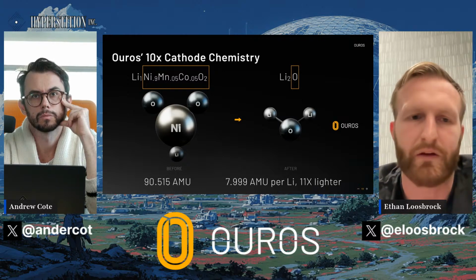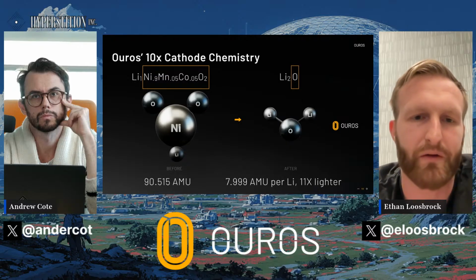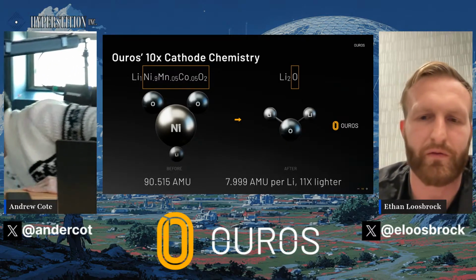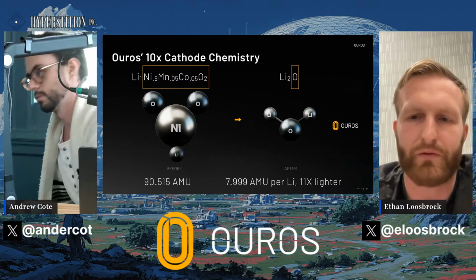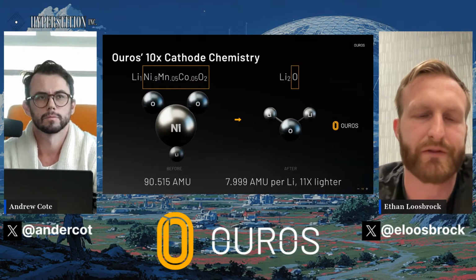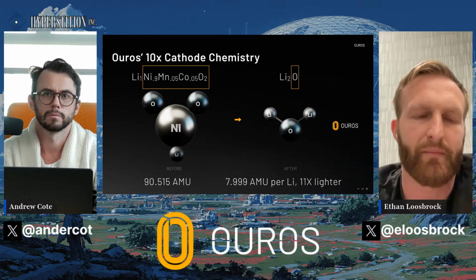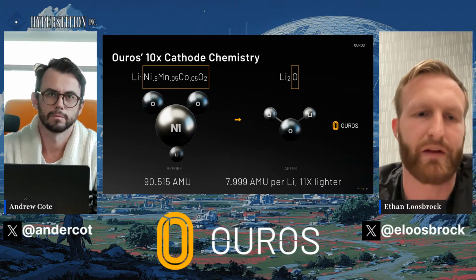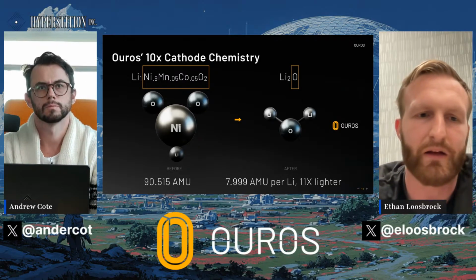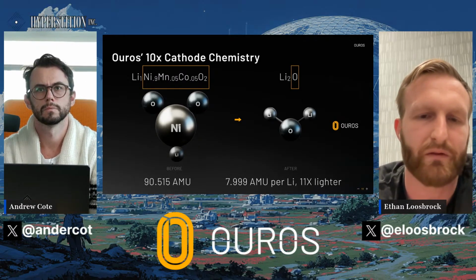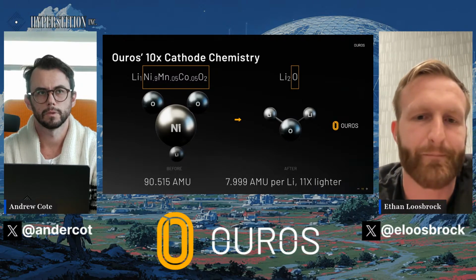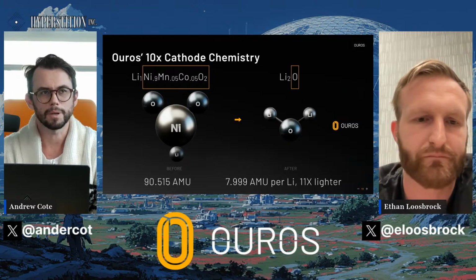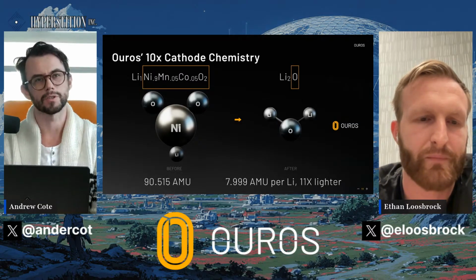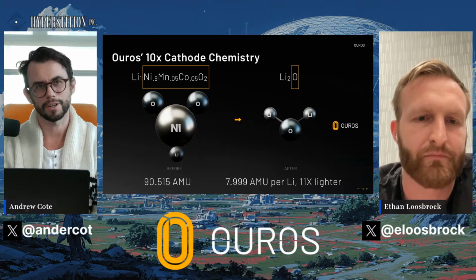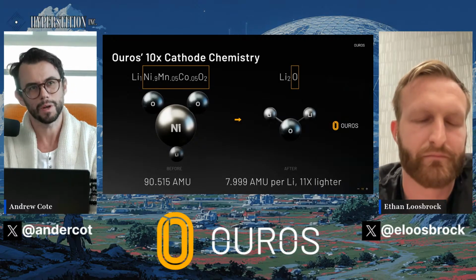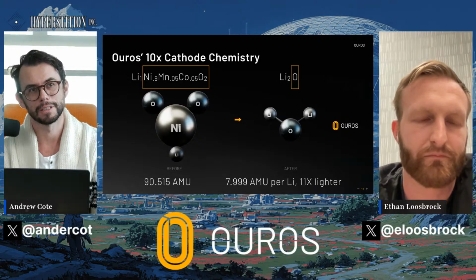Now you still have to incorporate the anode and the electrolyte and everything else, but ultimately Oros's plan is to get as close to the theoretical energy density of lithium oxide and then minimize the amount, mass and cost of everything else in the battery. So you want to make the battery look as close to the energy density of the materials as possible. Yeah, and this makes a lot of sense, based on our first-order intuition of the mass-to-charge ratio. Here we have these massive nickel atoms and these oxygen atoms that aren't really doing anything, and we store one lithium. Now we store two lithium for one oxygen.